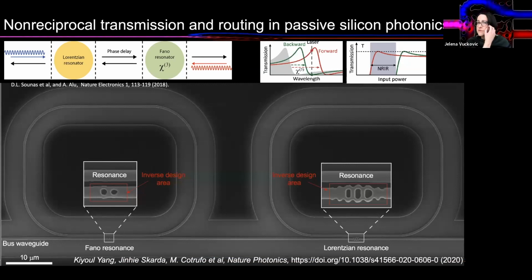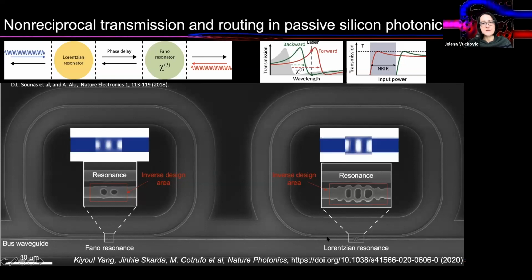But doing it at optical frequencies was difficult because you have to design these elements with the right transmission characteristics. Doing it by hand is pretty tedious and very labor intensive. I'm not really sure if it is possible to do it with as high efficiencies as we managed to do by optimization. But doing it by optimization is pretty simple. It takes an hour or so. So we started from a system of two racetrack resonators in silicon, and then just optimized the coupling regions of these two through the waveguides until we achieved the target transmission characteristics: a Fano resonance with a particular response here, and then a Lorentzian response here.